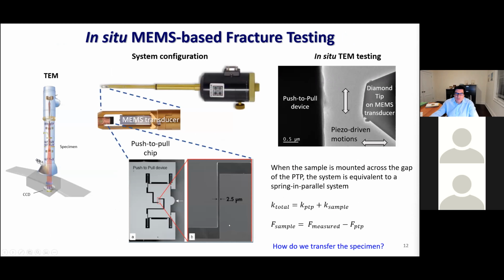So that was rewarding, but as I explained at the beginning, in this technique, we don't have control of the classical far field, low displacement type of problem. So we resorted to this other technique to achieve that control. And as I said, it's not shown here, but it's a MEMS transducer that will measure the force and the displacements.